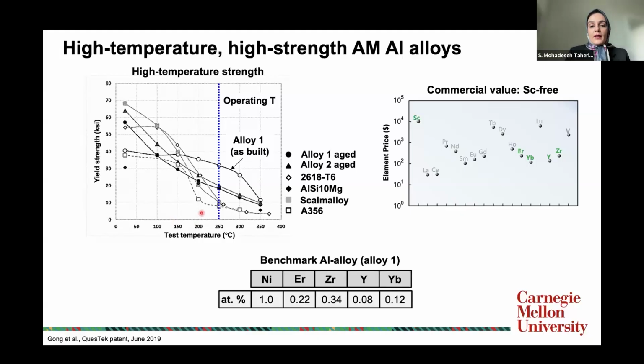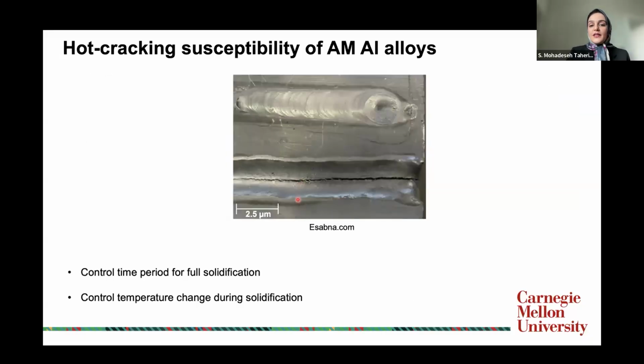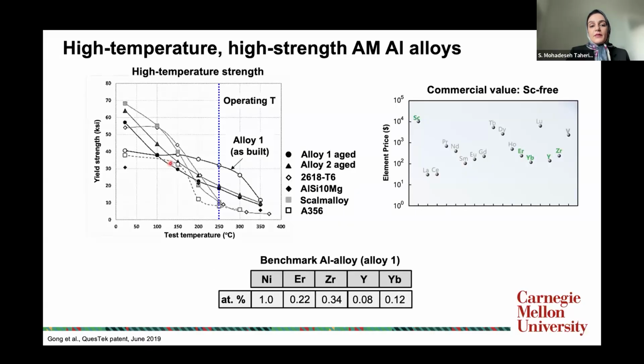At the time, although aluminum is a very vibrant class, you cannot print it because you see cracks during printing aluminum, and we call them hot cracks. Because of that, only a few classes of them you can print commercially. The most famous one was the Scalmalloy that has scandium in the composition, which has two orders of magnitude higher cost. But even among the available options, all of their strength significantly drops.